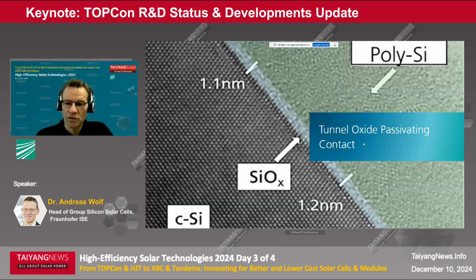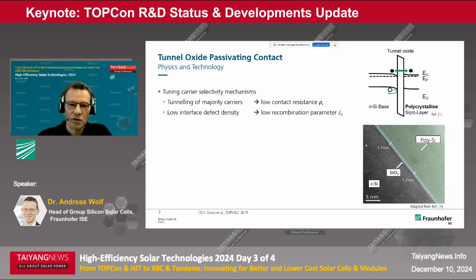So today the topic is tunnel oxide passivating contact. What's behind this? Tunnel oxide passivating contact is a carrier selective contact, and carrier selectivity meaning that you can extract the majority carriers easily through this contact, while the minority carriers are rejected. And this is realized by the structure that you see here. You have a silicon wafer, N-type doped usually, and you have a tunnel oxide layer, and the majority carriers can pass through this tunnel oxide by tunneling into the polycrystalline layer on the other side, while the interface is very well passivated by this oxide layer with low defects, which gives a low recombination parameter, and this gives the selectivity, which is key to reach high efficiencies in devices.